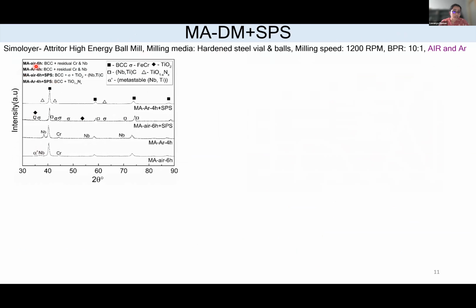Coming to the dry milled condition, we made these alloys using a similar high energy ball mill. Here the milling media was hardened steel vials and balls. This is a horizontal high energy ball mill. As I mentioned, we varied the milling atmosphere. We carried it out in air and argon. Here is the XRD pattern, which shows what phases we have. When we mill them in the powder state, we have a BCC phase and the residual chromium and niobium, like how we had in the wet milling scenario.